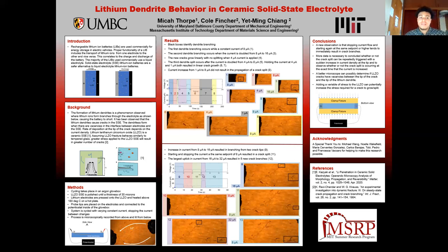From these results, we see that crack splits tend to occur when the current set point is increased, as well as starting and stopping at the same current rate. These results support a hypothesis that with the greater current, there'll be greater stress and greater flow of lithium ions into the dendrite tips, and therefore greater crack splits and faster growth of the dendrites.